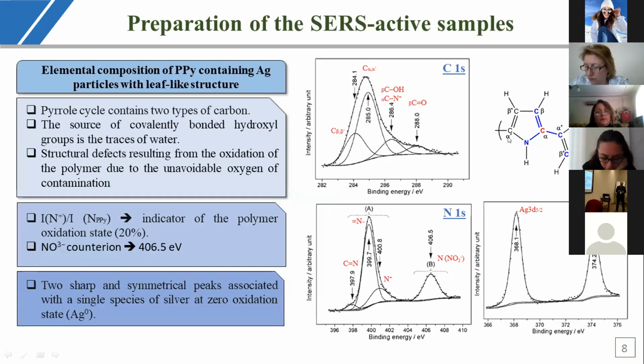The characterization of the polypyrrole silver composite was achieved with X-ray photoelectron spectroscopy. The carbon XPS signal contained 4 Gaussian components. The main peak at 285 electron volt is attributed to carbon atoms of the pyrrole ring at positions alpha and alpha prime. Knowing that the pyrrole cycle has 2 types of carbon, the peak at 284.1 electron volt is assigned to carbon beta, and the peak at 286.44 electron volt is attributed to the C beta-OH bond resulting from the presence of water. And finally, the peak at 288 electron volt arises from a carbonyl group due to the unavoidable oxygen contamination.